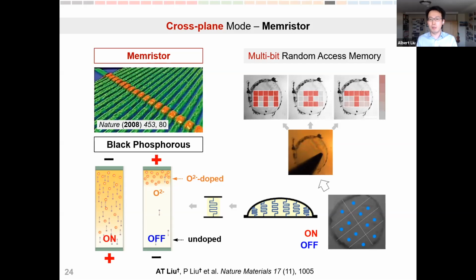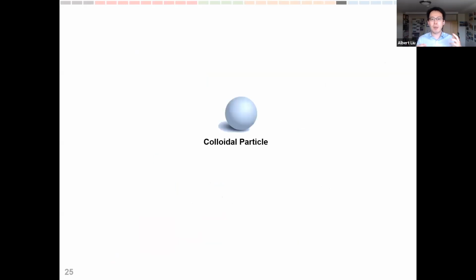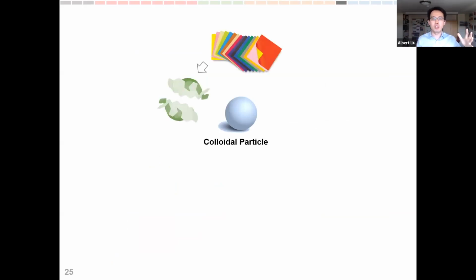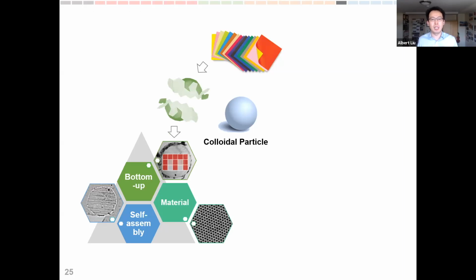So here, as a demonstration, we showed that we can write the letters MIT within a single particle through a vertical conductivity map. So here we're using an electrical probe to selectively write in the letters, and we're also reading out the letters and erasing the letters and writing again. So this is an entirely reversible process for us to store digital information within a cell-sized particle. So if you think about what we have done here, we take a colloidal particle and then wrap 2D material around it using controlled defect assembly to render a fabrication method for these colloidal electronic devices.